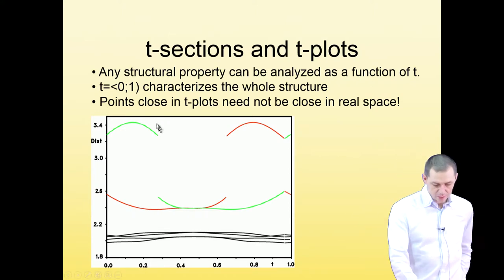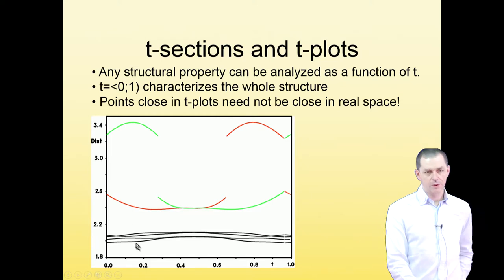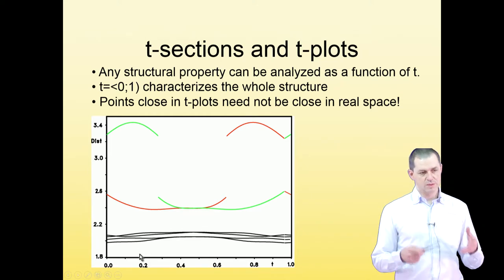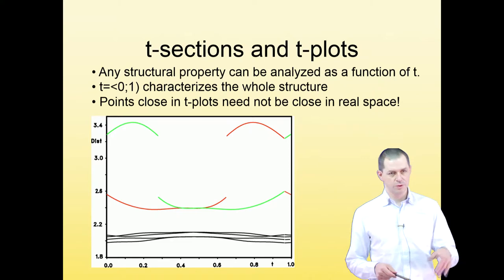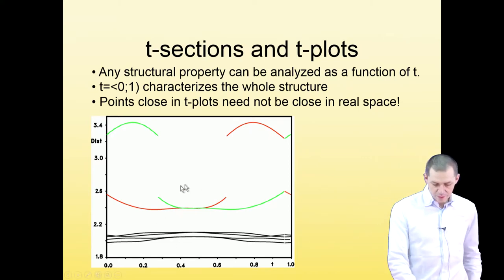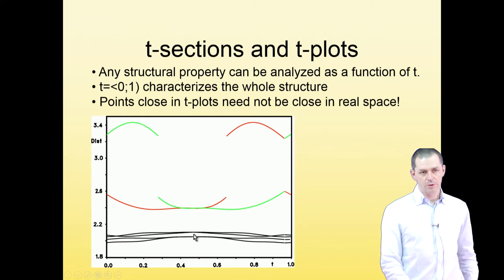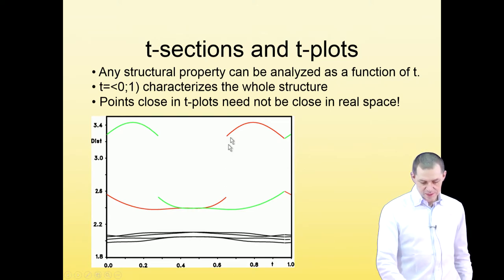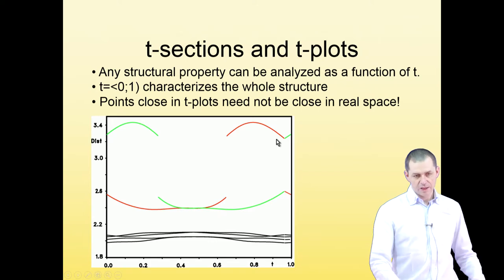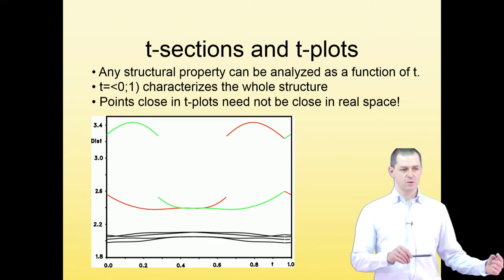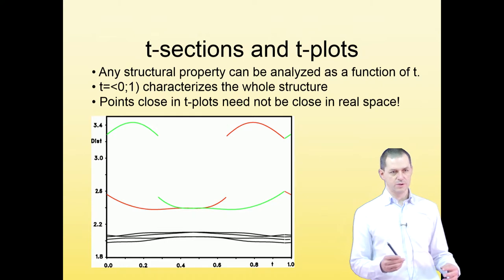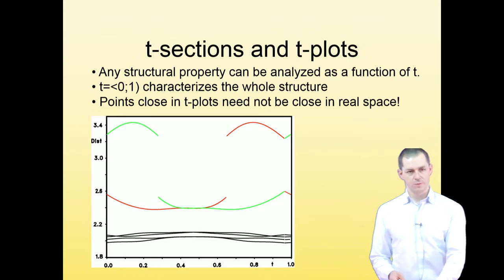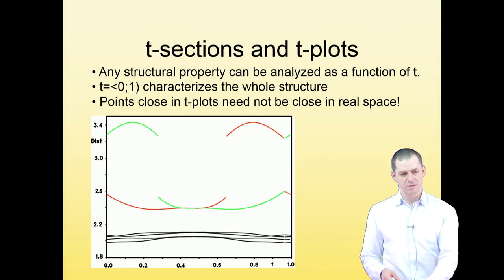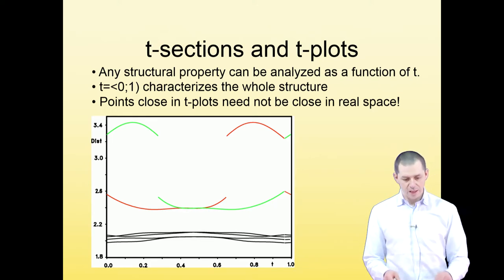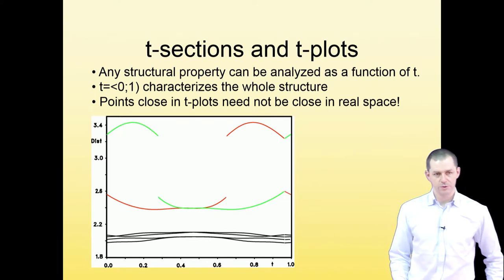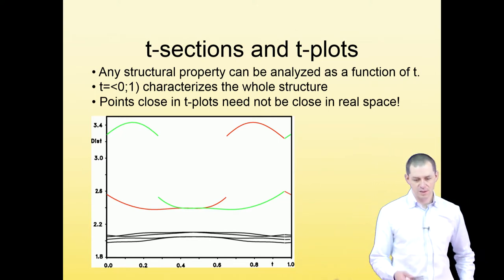So in the T-plot you can see three parts. In this part, the chromium has only five coordinated atoms. So this corresponds to the square pyramid coordination you saw at the beginning. In this part, it is sixfold coordinated. And in this part, it's again a square pyramid, but it is the other oxygen that is coordinating it. So the pyramid is facing in the other direction in the structure. You can't read the geometry from here. From here you can't say if this is a square pyramid or what it is, but you can say that there are certain variations of bond distances to chromium.